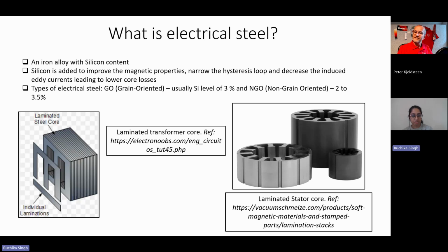Commonly, you use grain-oriented electrical steel for a transformer, and the reason being the flux in the transformer is in a particular direction with respect to the rolling direction. So you have better properties in that direction, and it is better suited for transformers. So you have higher magnetic permeability, lower losses in that direction. But in an electrical motor, you don't have a specific direction. It has different directions of magnetic flux. So you want to have uniform magnetic properties in all the directions you can get. And that's why you use non-grain oriented electrical steel in the second case, which is the motor. Yeah, so that's the reason.